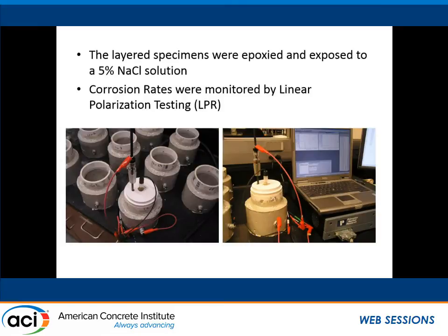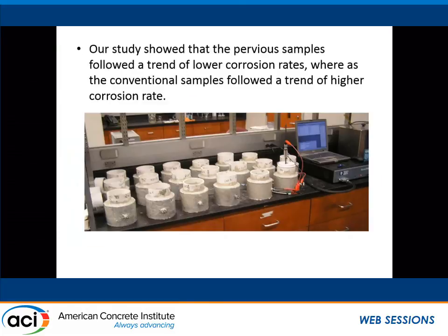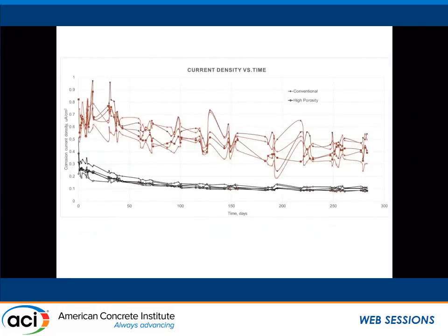You pond chloride solution for 2 weeks. You pour it off. You let it dry out, and you do dry, wet. So kind of worst case scenario for corrosion, and then you test it with linear polarization. The sides are all wrapped in epoxy, so we don't have any moisture movement in or out of it. So it's 1D diffusion. We got a whole bunch of samples. We've been running them for a long time now. Just to show you what we look at, we're way out at 300 days. We've been testing almost a year.